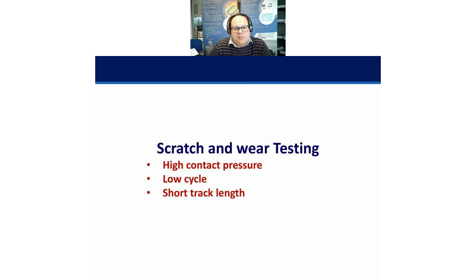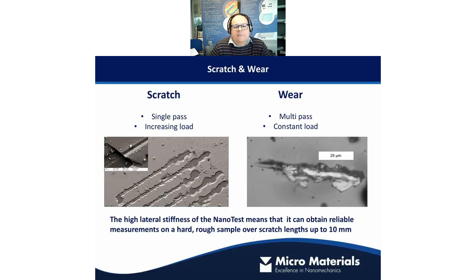So scratch and wear testing, so high contact pressure, a small number of cycles and short track length. So there's a couple of micrographs there. Here we've got some ramped load scratch tests. So there are 5 repeat tests here, actually scratched in this direction across the sample. And what you can see is a little bit of plastic deformation here up until this point where you get this great big delamination of the coating. So remember I was saying about trying to position a stress maximum so that you can actually fail the interface of the coating and the substrate. So that's a single pass ramped load or increasing load scratch test.